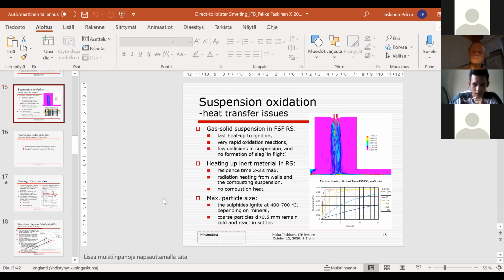But if we have something else, you mentioned rare earths, they are forming such stable oxides that they deport in slag. Rare earths are like lime or MgO in terms of the stability of the oxide. So you can't recover rare earths from copper making if you don't treat the slag. They are all going into the slag phase. And if you are treating the slag with some hydromet methods, that is then possible, but not from blister copper.